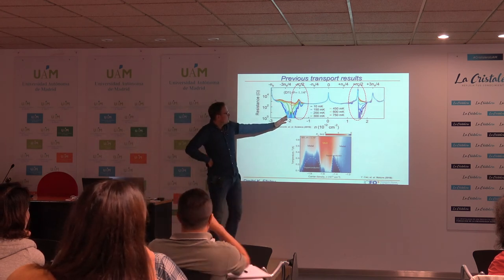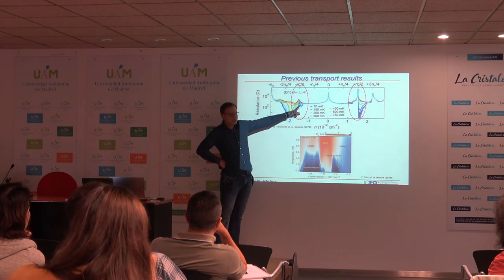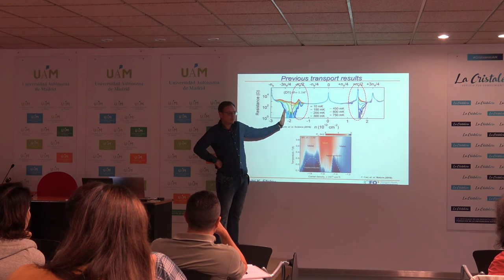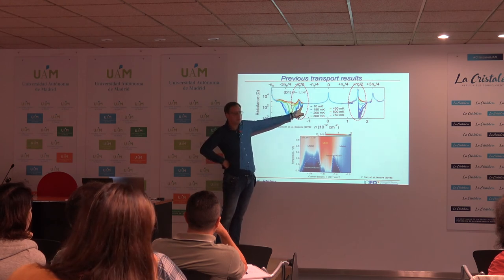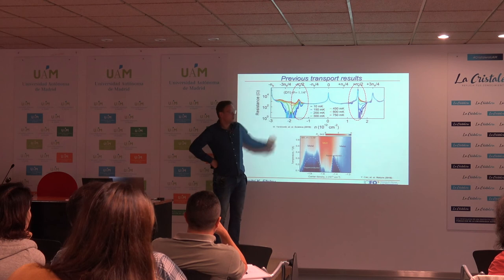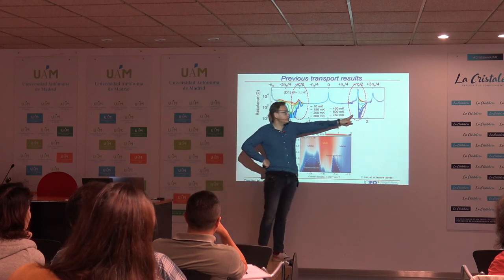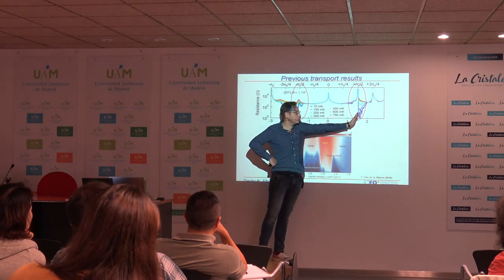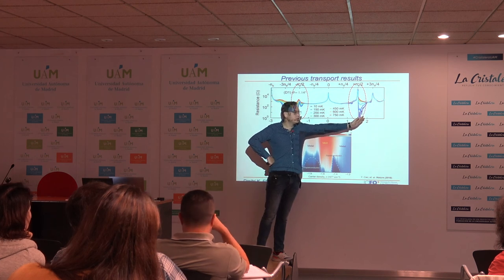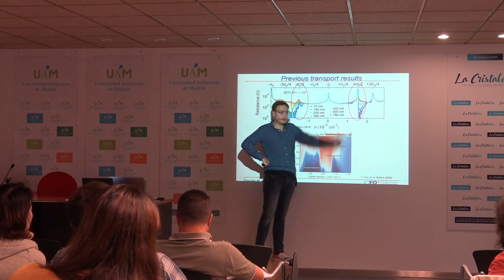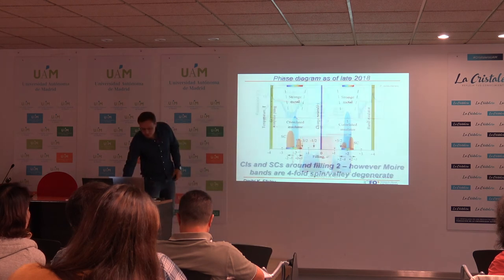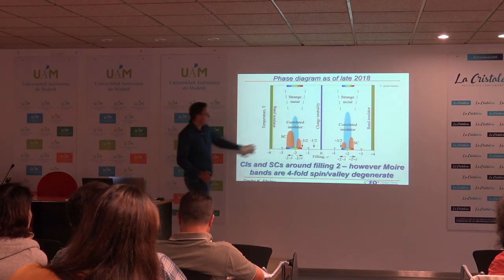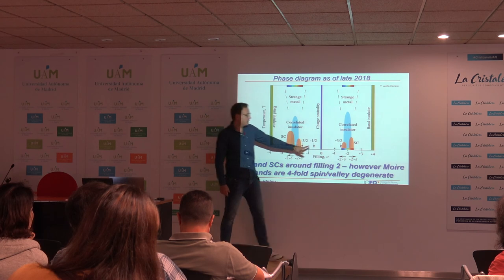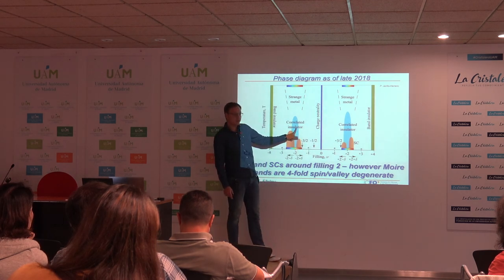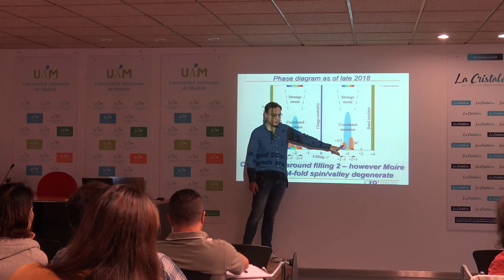The data from Columbia shows a very weak correlated insulator here, which is almost killed by a really large superconducting state here. And they don't see a superconducting state on the right-hand side of that insulator. So let's take a look at this insulator. This insulator is really strong. There's also superconductivity only on one side of it, but none on the other side. So in this picture, that would mean they don't see this superconductor, they almost don't see a correlated insulator here, and they don't see this superconductor.